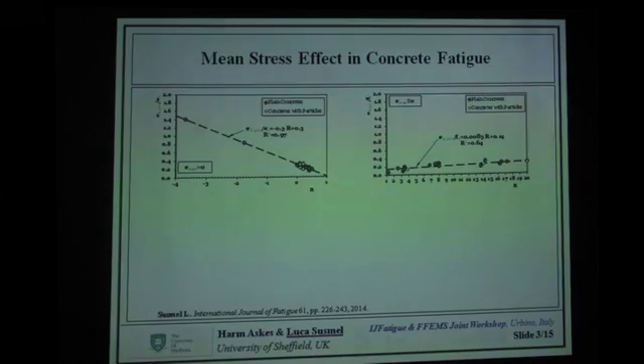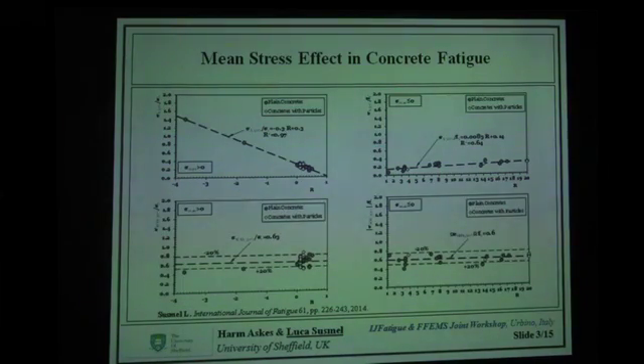But if you use the design stresses as we defined them before, you can see that even if there is a certain level of scattering, the normalized endurance limit in terms of extremes of the cycle allows the data to fall within a quite narrow scatter band. So the idea is that we can directly take into account the mean stress effect by using these tricks, that is the extremes of the cycle, to perform the design. And according to this general idea, we had to manipulate the theories we are using